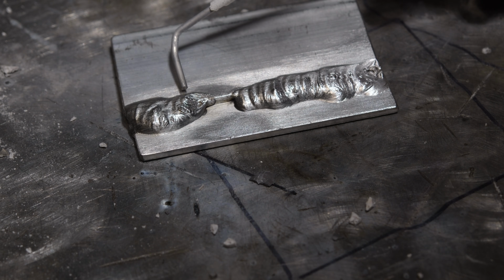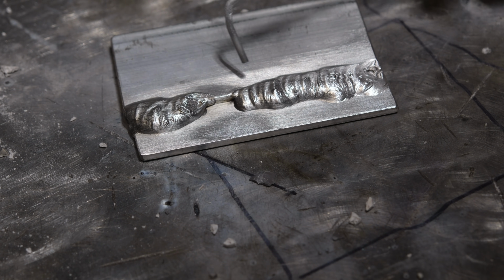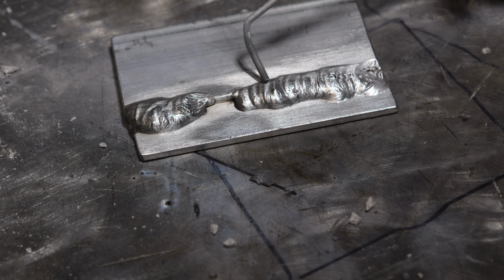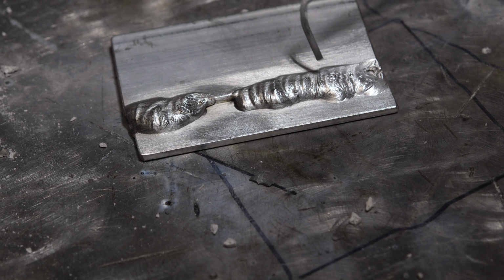And that's realistically the biggest issue with running DC negative and just straight argon, is that you just can't see what's going on, so you will have defects. Speaking of defects, I polished this with a wire wheel just to clean up the smut that was on here. You get a lot of black soot doing this because of the magnesium, and you might have saw the green arc. That's also due to the magnesium burning off.